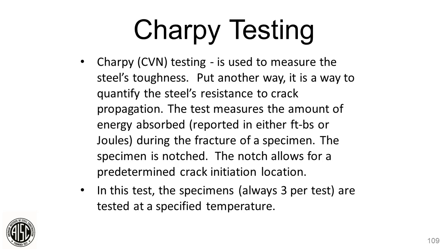The problem is the expense of getting the sulfur down. It's hard on the ladle life, and the other thing that can happen is you have very high potential for breaking rolls at those low rolling temperatures. So that's why producers would shy away from that. That isn't to say it can't be done, and it is done on some products, but the mill loads can get too high, and you're taking a risk whenever you're trying to hit those real low temperature Charpys, the minus 50s. Minus 20s aren't as bad. They're pretty common anymore, but not on everything, obviously.